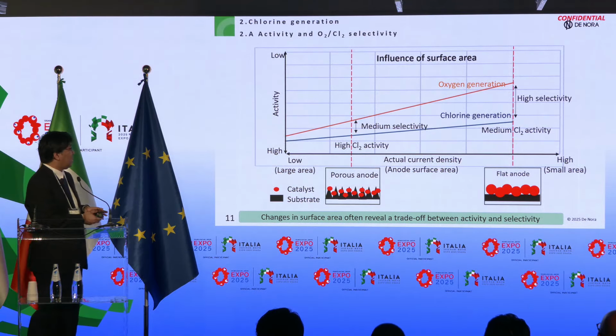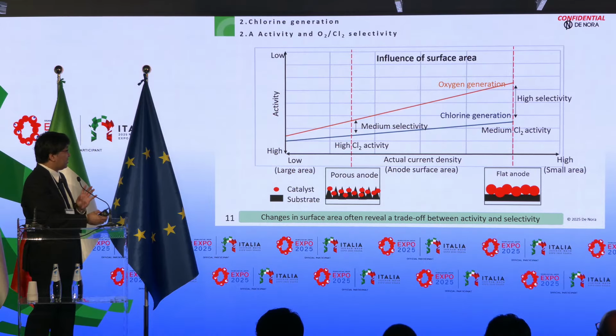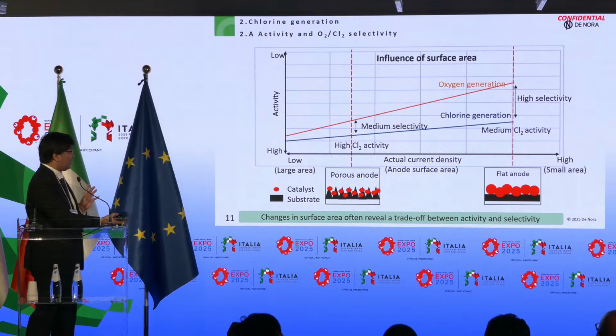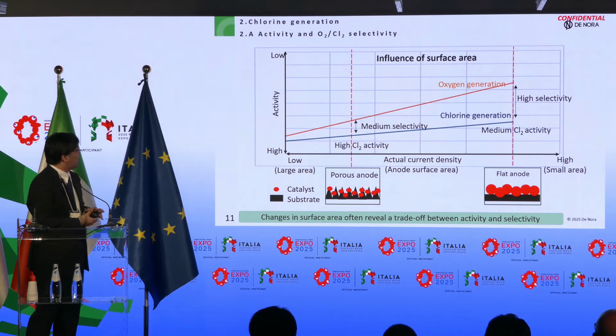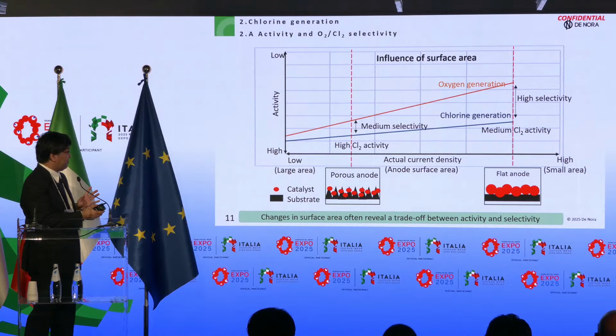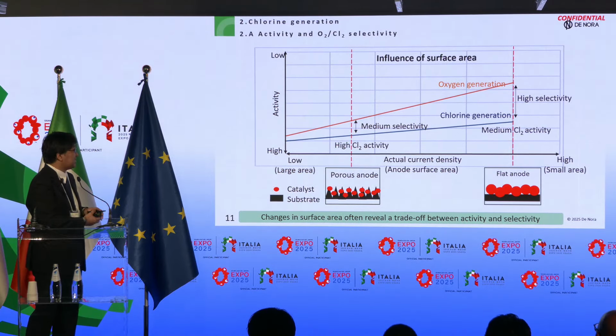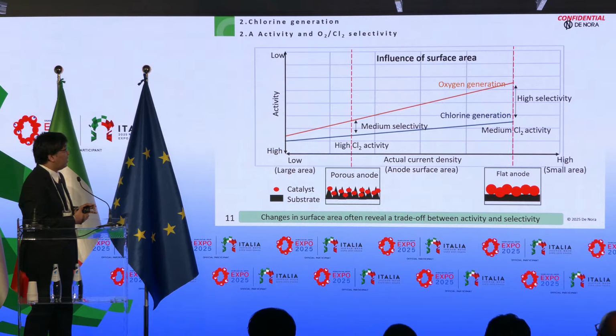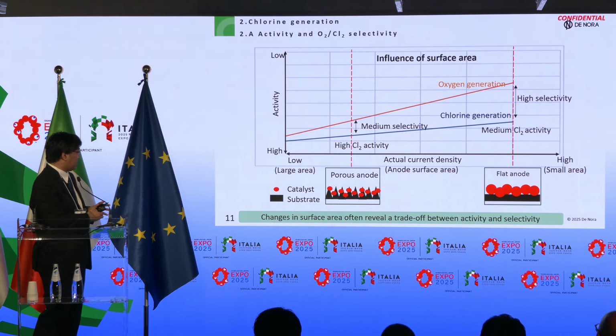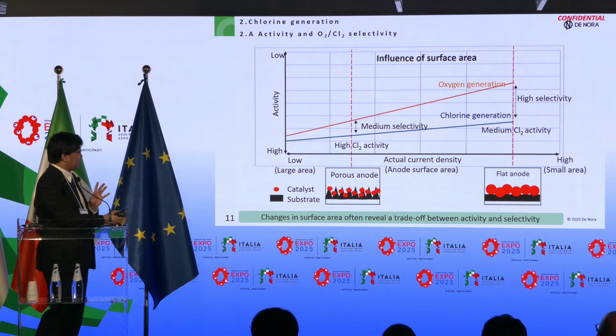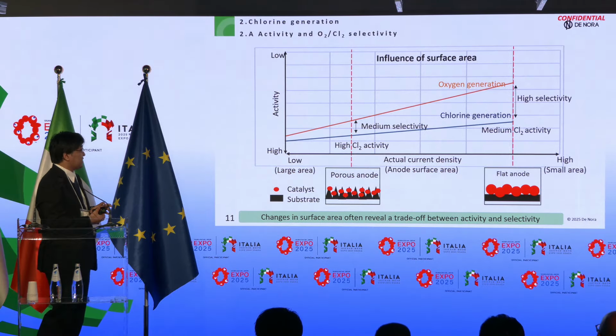On the other hand, in case of a large surface area anode, it shows very low overvoltage because of very low actual current density. But oxygen overvoltage also decreases, so selectivity will decrease. That's why sometimes oxygen and chlorine selectivity and chlorine generation activity show a trade-off relationship.